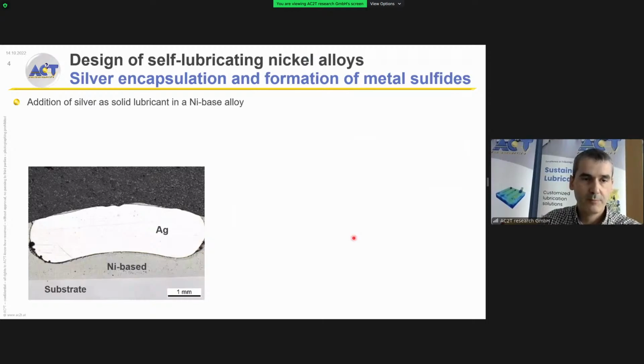The point is that, for example, if we have a nickel-based alloy and we want to make it self-lubricating, we need to add some solid lubricants. For example, silver is a soft metal with low shear properties, but nickel and silver are not miscible. So if we melt them with a laser, we end up having some microstructure like this. So it's a substrate with a nickel-based coating with a huge silver bubble on top of it. So this is completely useless. It's just a fancy way of wasting silver.